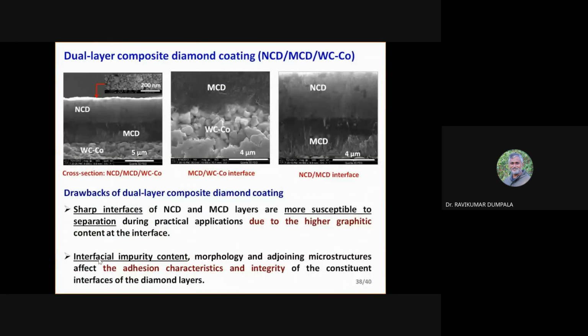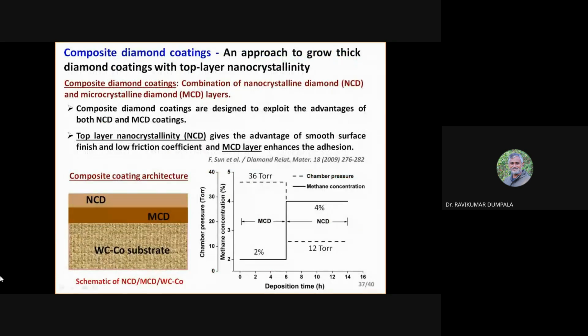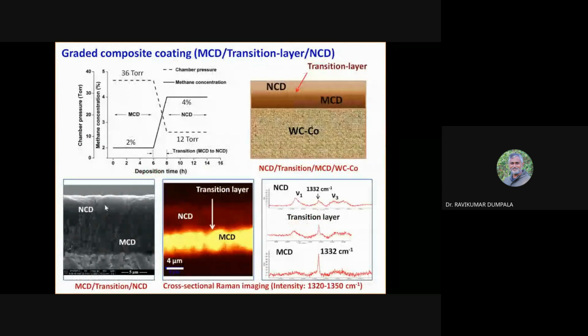So, some characterization. I won't go into much detail on this composite coating. I mentioned how you do the coating. Sometimes what happens is that when you coat NCD on MCD as two layers, the top layer's adhesion is again not good. It may come out very easily. That's what we understood while doing some tests. Then, as in the top right side figure, instead of having clear-cut different layers of MCD and NCD, we developed a technique where a transition can happen, a gradient from microcrystalline diamond to nanocrystalline diamond.